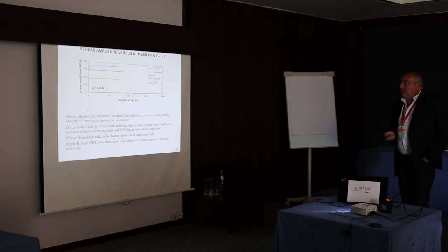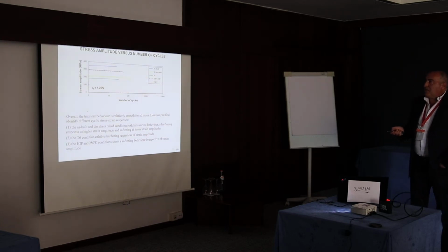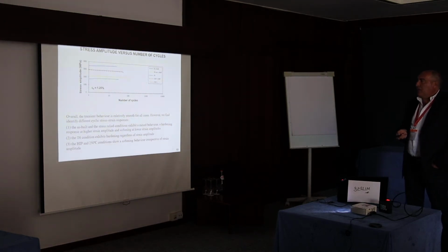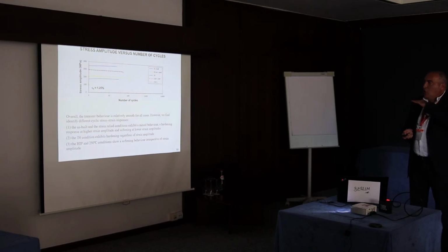This compares the stress amplitude with the number of cycles. We can see that the transient behavior is relatively smooth for all cases. However, we find and can identify different cyclic strain responses.